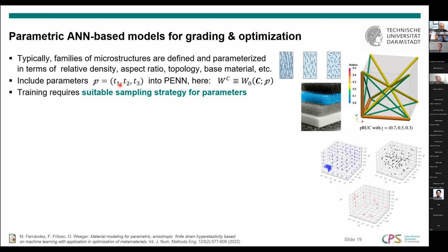And for this now, basically we have to sample the space of deformations, but we also have to sample the space of design parameters. And here, basically, we use a sampling strategy for this unit cube of design parameters, where we choose some regular points on the boundary of the parameter space, combined with a Latin hypercube sampling of the interior of the parameter space. Because we found that it's very important to have points on the boundary, which means that you really always interpolate in your design space. And we formulate now here a model in terms of the neural network based on the right Cauchy-Green tensor and the parameters. So we did this before we developed the convex model, which is why we did not use the convex model over here.